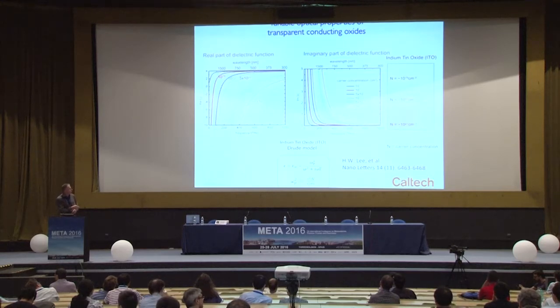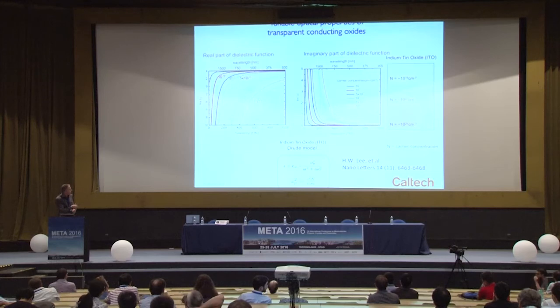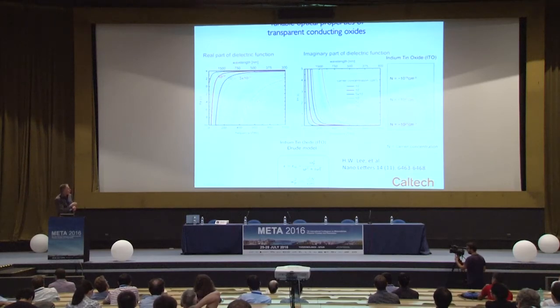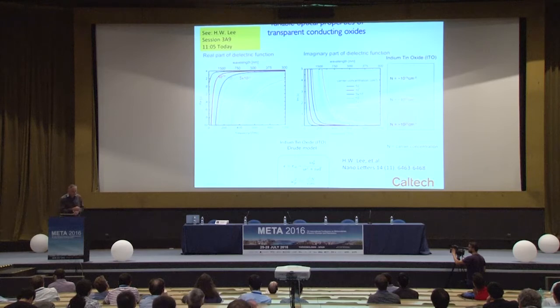You can see this just by your own eyeball spectroscopy. If we look at a film of indium tin oxide that's doped from 10 to the 19, 10 to the 20, 10 to the 21, you can see the color change due to the imaginary part of the complex index changing. These are simple Drude model fits for the real and imaginary part of the complex permittivity. And you can see here that indeed across the visible to near-IR, this is exactly the carrier density range that leads to a change in permittivity from positive to negative. This will be expanded on in the presentation of Howard Lee later this morning.